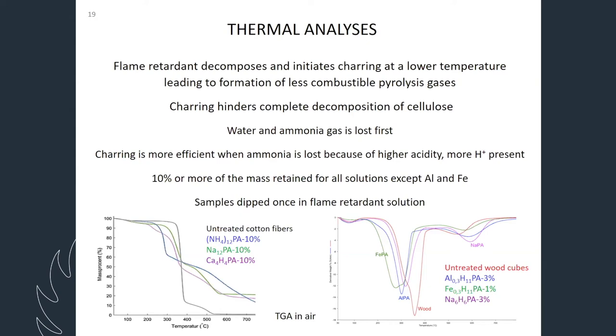For the treated samples, there is much more mass left. We have seen a bit less for aluminium and iron treated samples, but we used very low concentration. Maybe that is the reason they lost. In those cases, weight loss was a bit more. And so far, what we have tested, all the samples we have dipped one time here. Multiple dippings we didn't display.